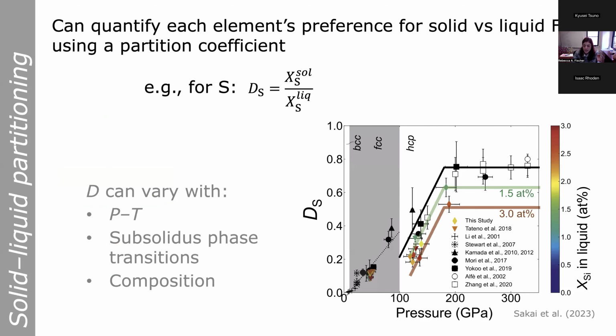So this figure is from Sakai et al. 2023. I'm showing the partition coefficient of sulfur versus pressure. The black symbols and curves are for just the FeS binary system. And you can see at low pressures, D tends to increase with pressure. There's perhaps a discontinuity here when the solid changes from FCC to HCP. Then it continues going up, and then somewhere around 200 GPa kind of flattens off and stays constant. But it's also affected by composition. So for example, the various colored symbols show different amounts of silicon in an iron silicon sulfur ternary. And in this case, it shows that adding silicon lowers the D of sulfur.